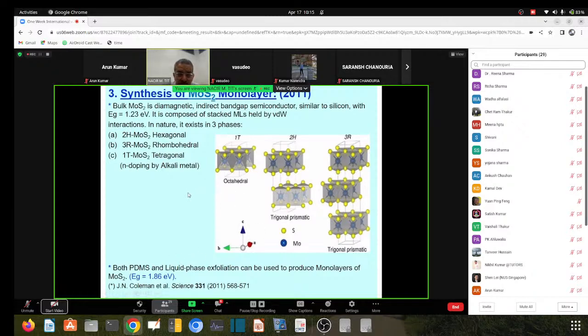And it has a second structure, which is 3R, 3 rhombohedral, and one more structure, which is the tetragonal structure. The first 2 structures have trigonal prismatic symmetry, whereas the tetragonal has octahedral symmetry. The metals have octahedral symmetry. Anyway, the method to grow the monolayer, because we are concerned with monolayers, is either from the top-down technique, like exfoliation, or it can go also from the bottom-up technique.